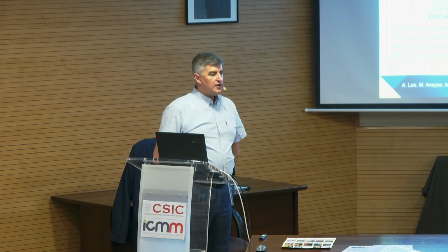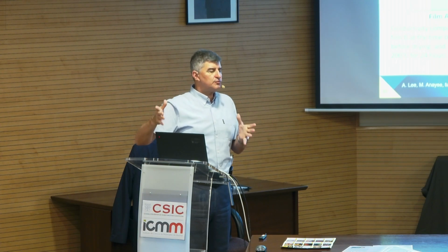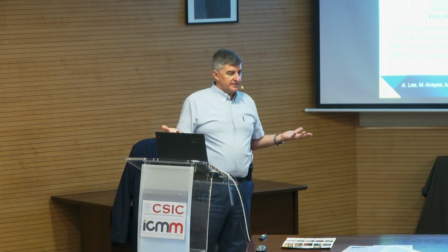More questions? How big can the flakes be prepared? So far, by solution processing, we know how to make flakes in larger quantities up to about 20 microns in lateral dimensions, which is again very big for solution processed materials. Single flakes we were able to make 40 to 50 microns, but that is for single flake studies. Fundamentally, there should be no limit. Also, people are starting to work on CVD.